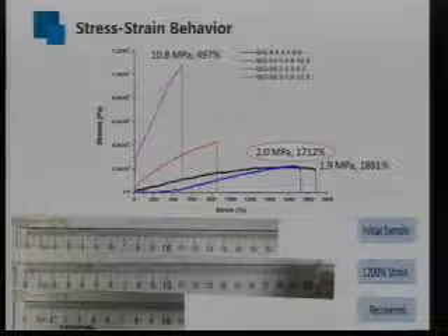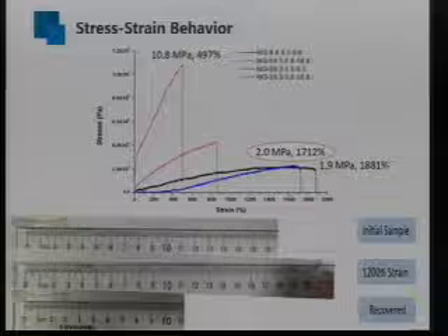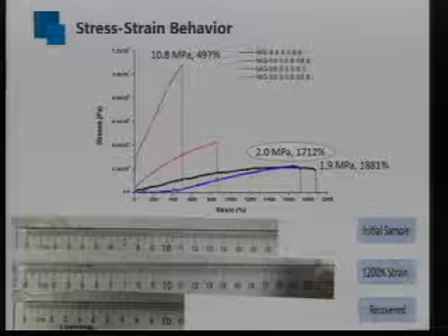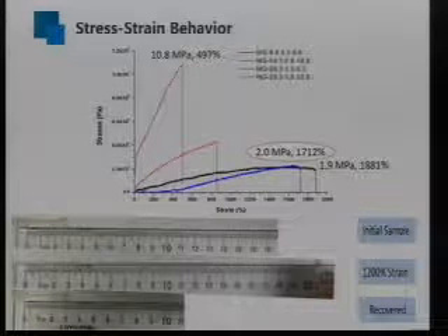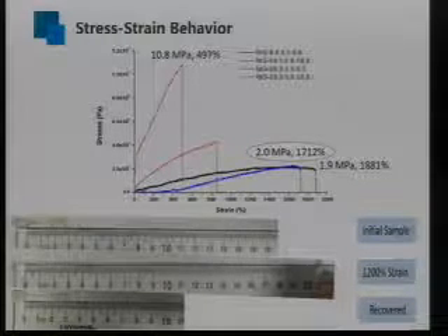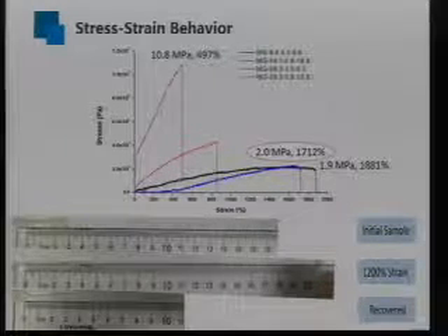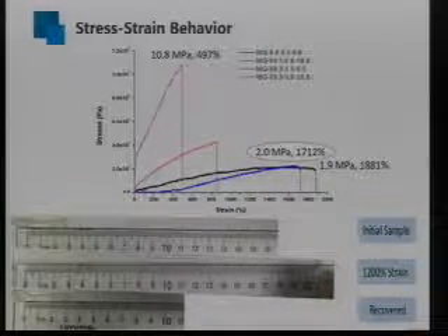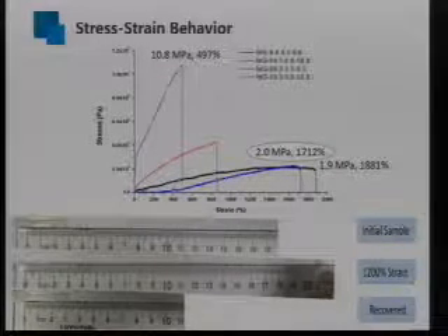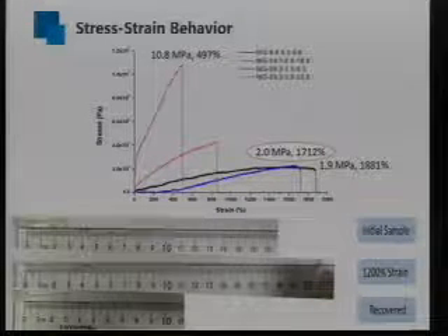So this is much beyond the commercial products, with mechanical strength always lower than 1 megapascal and elongation always lower than 500%. This specimen can be stretched to even as long as 12 times its original length, and it can still recover to its original shape with less than 15% strain loss. By the combination of this elongation higher than 1700% and its very good strain recovery, the acrylate multigraft copolymer superelastomer was successfully synthesized.